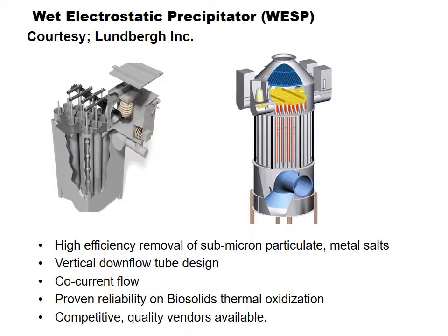So there are other wet electrostatic precipitators where the gases are going up and the water's coming down, and they're smaller tubes. This is an ideal situation for corrosion and fouling. Corrosion typically is less prominent when you keep it wet all the time or you keep it dry all the time. When you have upflow, you get an area in the middle where it's kind of wet, dry. Downflow is water and air moving in the same direction.